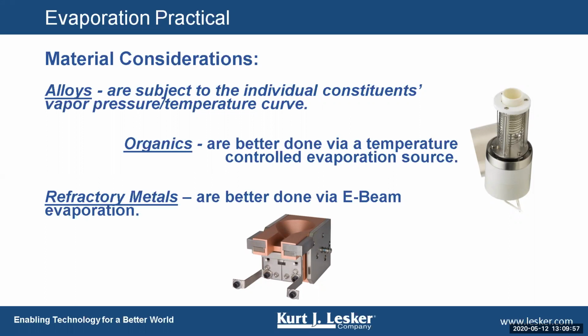To reduce chemical reaction to the source during venting, do you have any recommendations of a waiting period after turning off the power to the source? It just depends on the source and the material itself, but as a rule of thumb, I wait 20 minutes. Sounds like a long time, but 20 minutes on either a resistive thermal setup or an E-gun is quite sufficient to cool the material down to the point where generally it's at room temperature or slightly lower, depending upon the chiller set point, and it's less likely to interact with the ambient atmosphere.